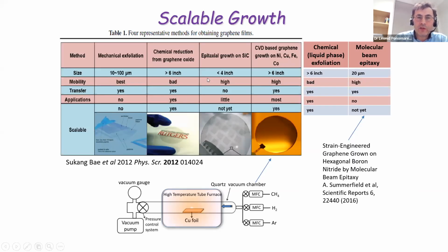For example, using a method called chemical reduction of graphene oxide, we can indeed produce tons of very tiny, small graphene flakes, which are just a few nanometers across. This material can be used, for example, to make composite materials, to reinforce some plastic, something like that. But this is very, very far from applications in electronics. The most promising method is called chemical vapor deposition.